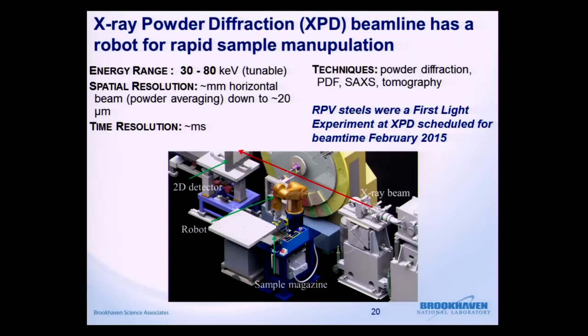Some of the other features that are essential about XPD for our work is the energy range. Since it's a high energy beamline, we're able to look right through our steel samples. So we look at the samples in transmission geometry. The X-ray beam passes completely through our sample. Also, the spatial resolution. It has a fairly large spot size, so we're able to sample a lot of the material at once. We're able to see many grains of the material at the same time, which is also important. And of course, it has extremely high flux, so each of the measurements is very short. That also enables high throughput, and it really makes sense to have a robot at this type of beamline. And these RPV steels were a first light experiment in February.